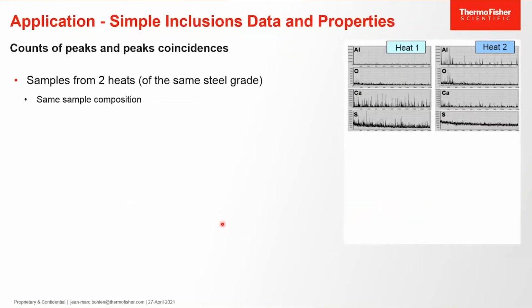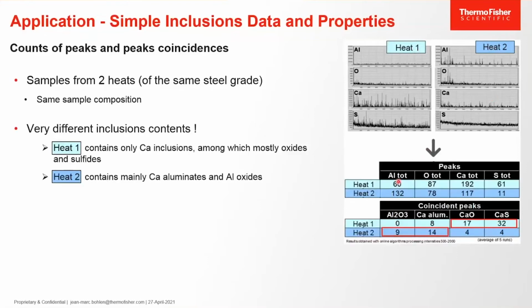In this example, we have counted peaks and peak coincidence in samples from two different heats, of the same steel grade. Maybe not necessary to mention that if you measure them with optical emission, you would measure the same composition. So as you can see in the run charts, the sample of heat one and heat two have pretty different inclusion content. So by using a very simple algorithm to count the peaks,